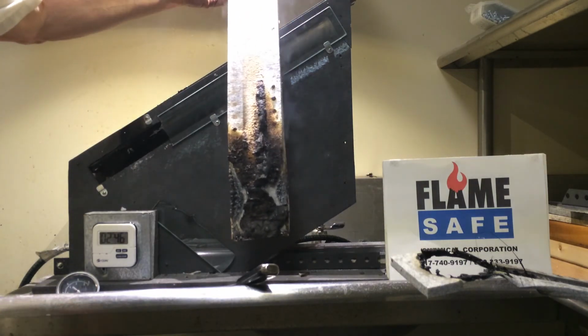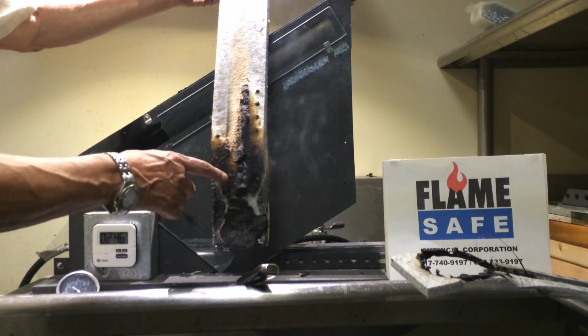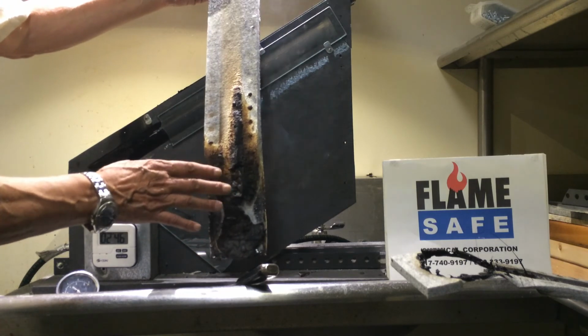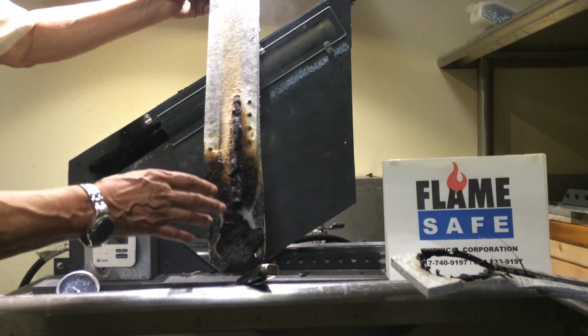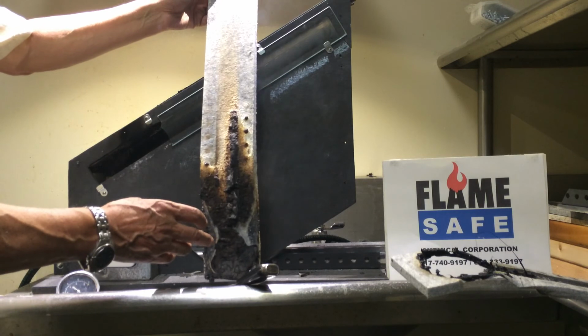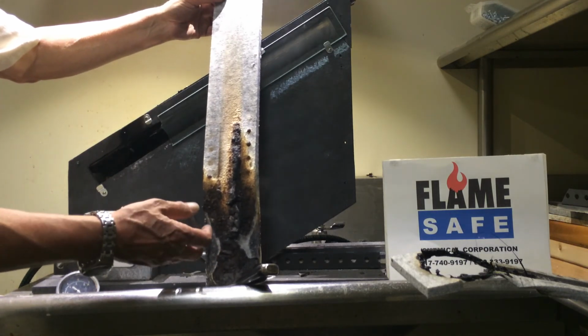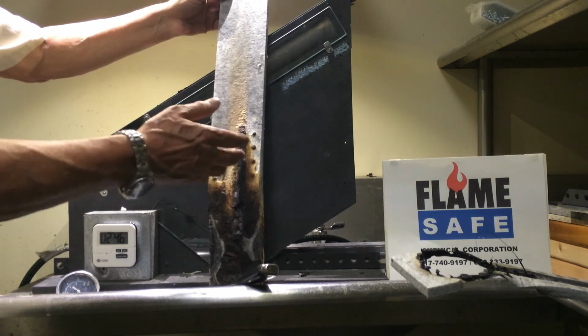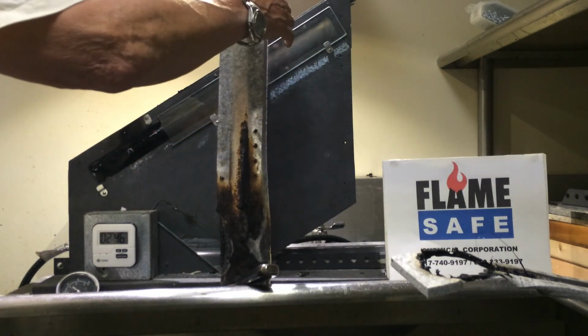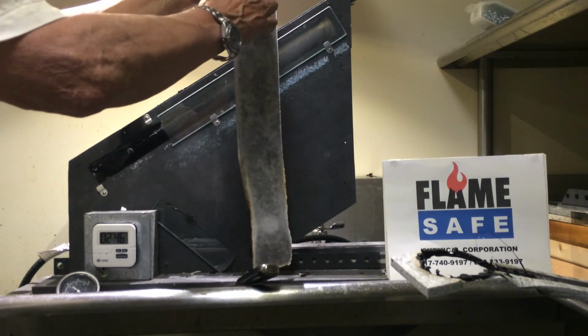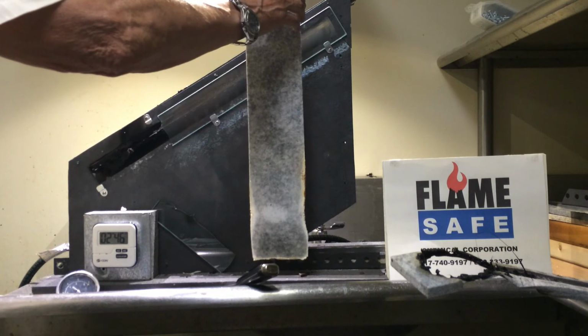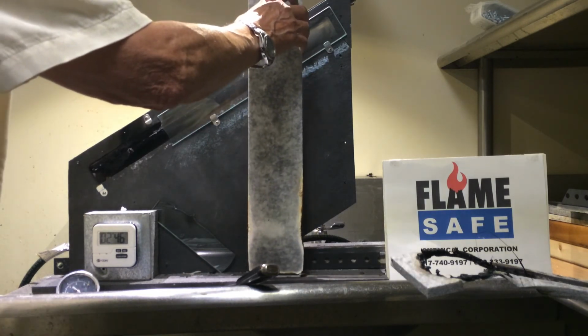Please take note. If you'll notice, the expansion, that is called intumescence. That is the carbon char. That's an expansion of the coating that protects the substrate. If you'll notice, even after 6 minutes, there was no burn through on the coated specimen.